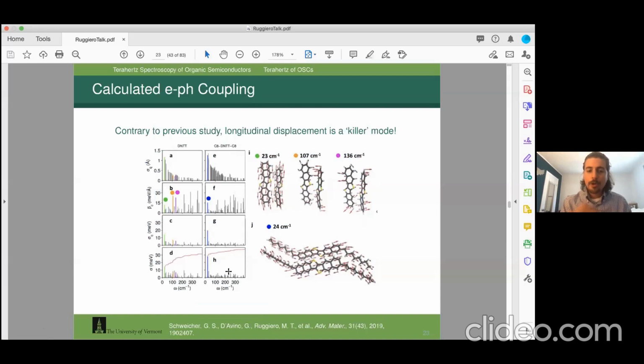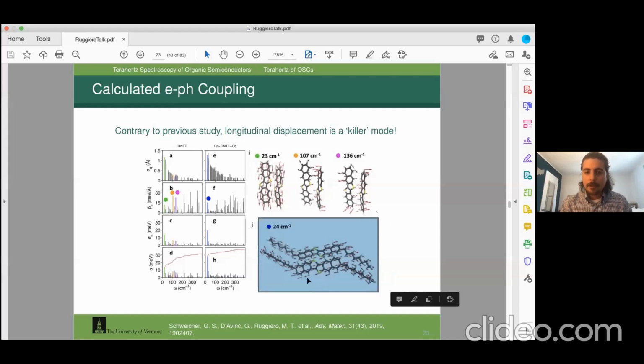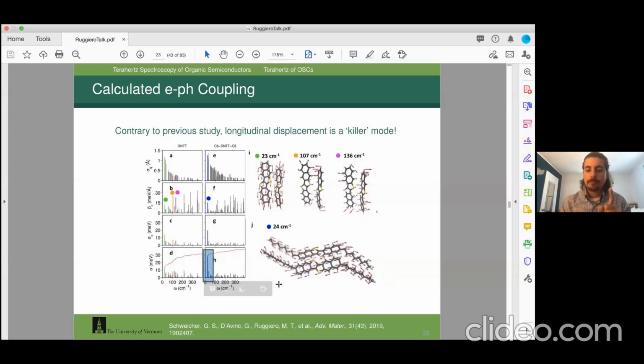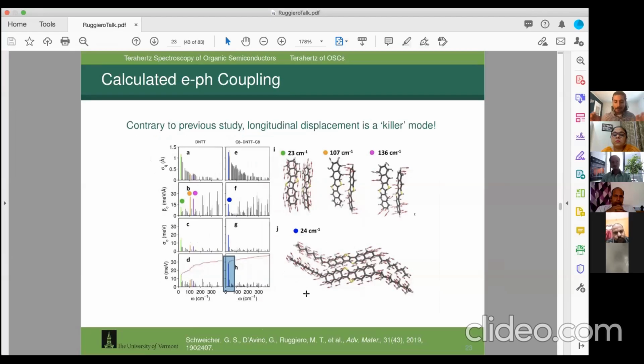What we really found is a powerful result: in this material, by calculating it, we've found one single motion that contributes about 90% of the bad electron-phonon coupling in these systems.